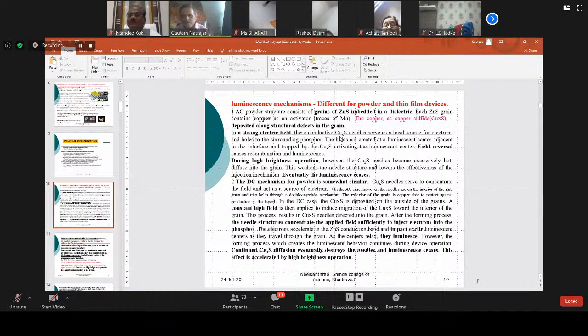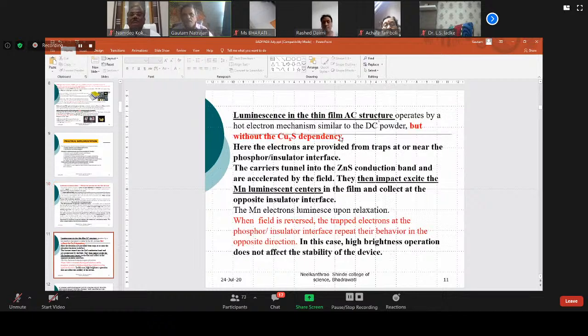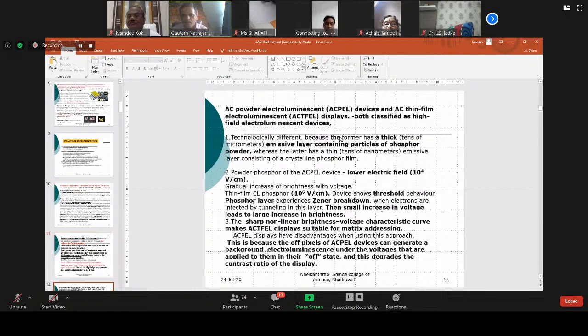Here, since the field is reversed, that section is not much affected. Here, the field cannot be reversed. So when you use it for a high brightness DC lamp, the lifetime will be very short. And the luminescent thin film AC structure is very similar, what they call the hot electron mechanism. Hot electron means higher energy electrons hitting the luminescent center. That's what it means. Impact excites the manganese luminescent center. That is the point. When the field is reversed, trapped electrons at the phosphor insulator surface repeat their behavior in the opposite direction. So, in spite of high brightness, the stability of the device is good.